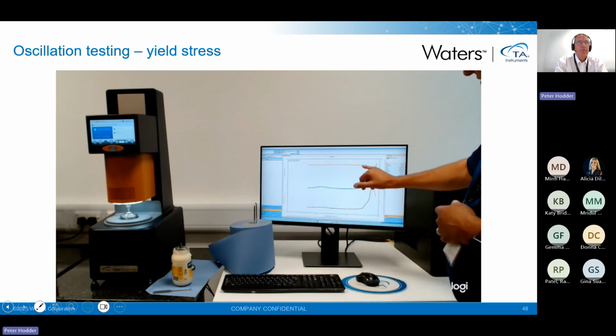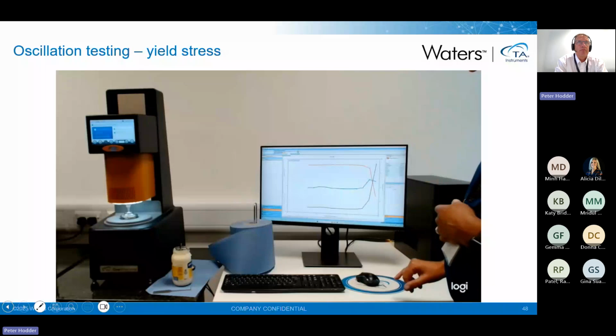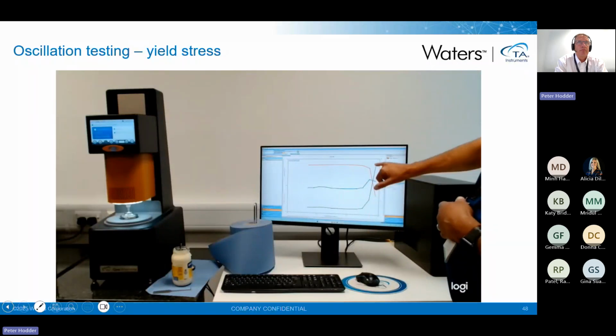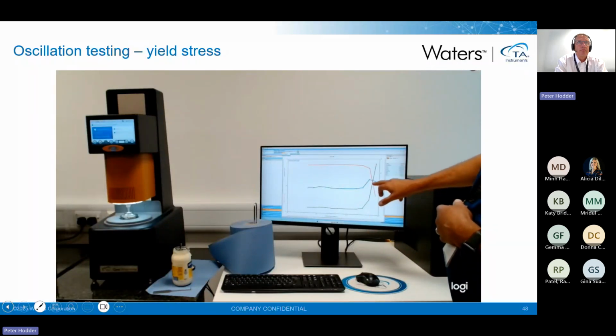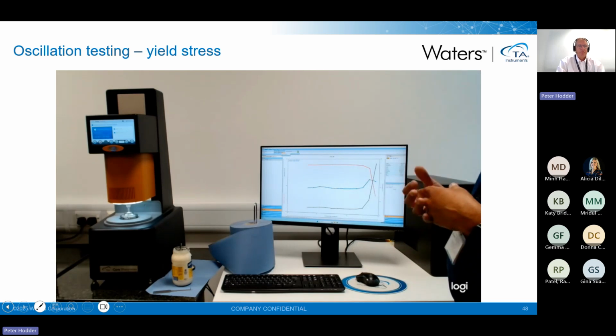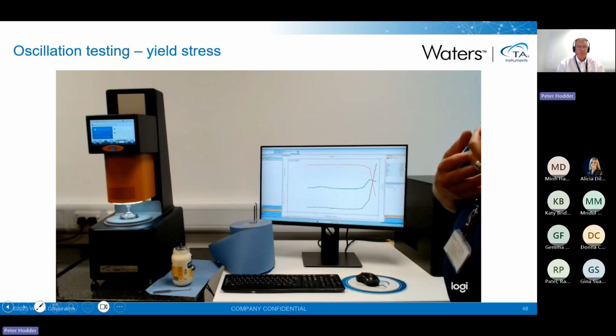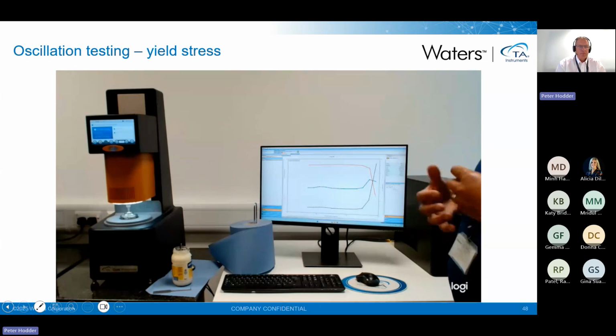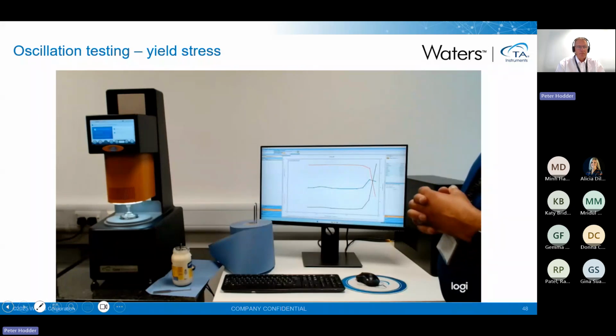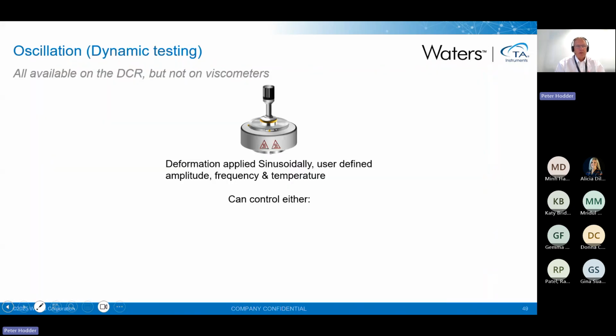And then as we see that the sample breaks down, as we yield, we see the rapid increase in the phase angle. And when the phase angle goes through 45, G prime and G double prime cross over. So the sample becomes, instead of solid dominant, liquid dominant. So it's physically changed its state of nature. And as a result, you can imagine that the sample will behave now more like a liquid than it would as a solid.